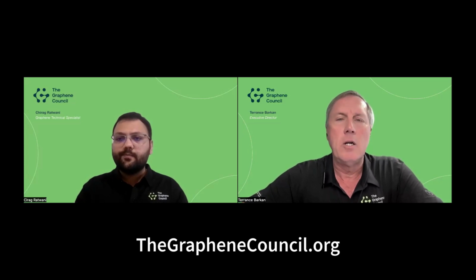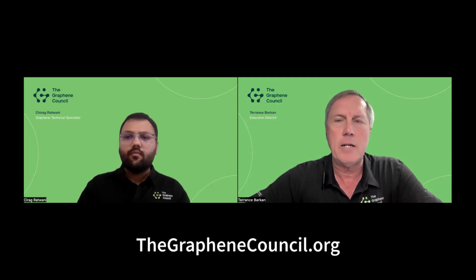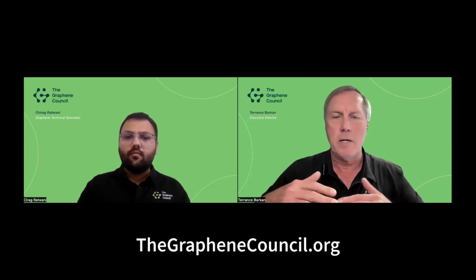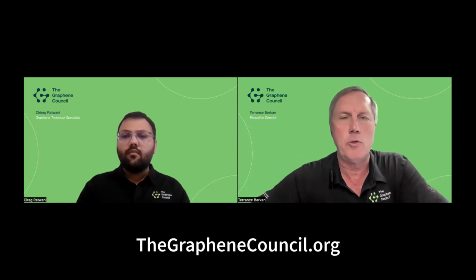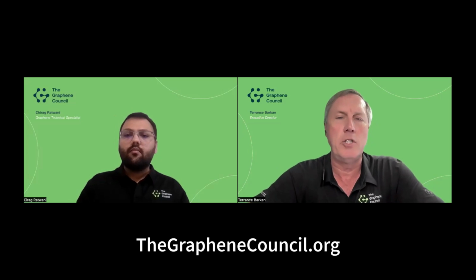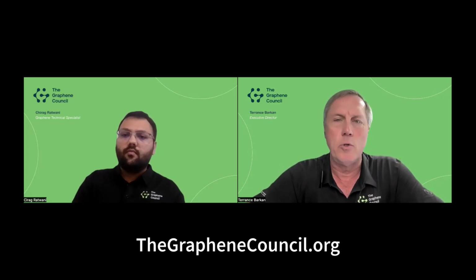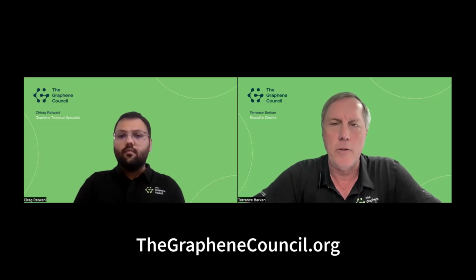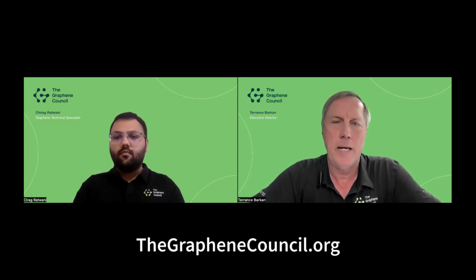Having said that, graphene and carbon nanotubes can be used together. And in fact, when you're trying to create electrically conductive nets, we've seen that carbon nanotubes and graphene used in combination can be more effective to create that conductivity than using carbon nanotubes by themselves or graphene by itself.